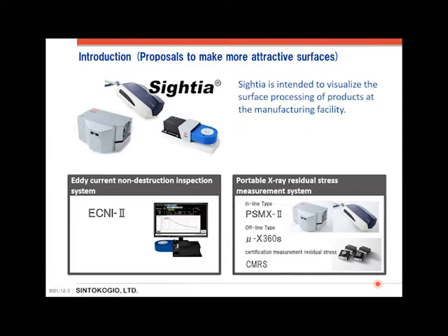Until now, you have been using the 0 megapascal iron powder to confirm the measurement values. However, the residual stress value of the target part is not 0 megapascal, but the measurement equipment is calibrated at 0 megapascal. The material being evaluated is bulk, but it is checked with metal powder. Don't you feel uncomfortable? The CMRS was created to meet the needs of those who want to confirm the target stress value with the same material.